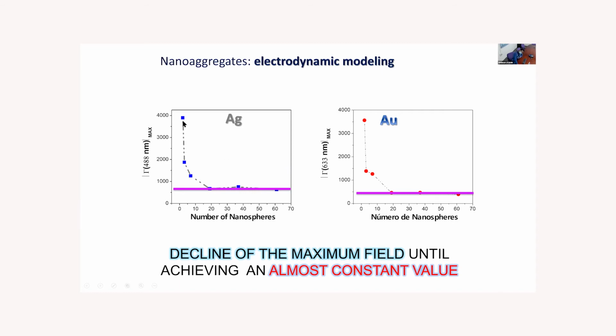The clusters with the highest enhancement are the dimers, or these small clusters. When you start to have very large clusters, the enhancement is more or less always the same. So that's the message: if you want to have a very large enhancement factor, you should find the condition where you aggregate your colloids, but not to have very large clusters, only to have a cluster of 3, 4, or something like that in the number of nanoparticles.